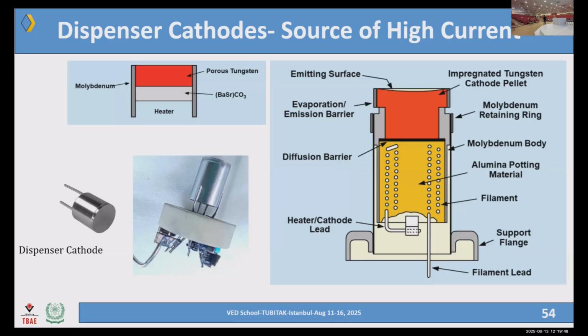Professor Yaqub was mentioning the magnetic field. Yes, the magnetic field. So imagine the delicacy of this instrument. It is just very thin. Probably I can fit one on my nail. Even then, the heater is wound, because you cannot even tolerate the fluctuation of magnetic field on the surface, because eventually the barium is deposited like a carpet, and the carpet is only one atom thick. I don't know if we should be using the word thick, but the height or the thickness is just one atom. Monolayer, yes, monolayer of it.